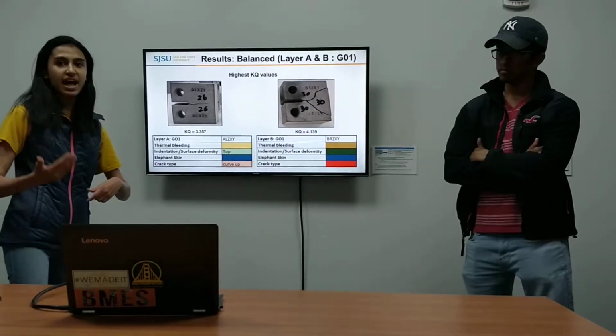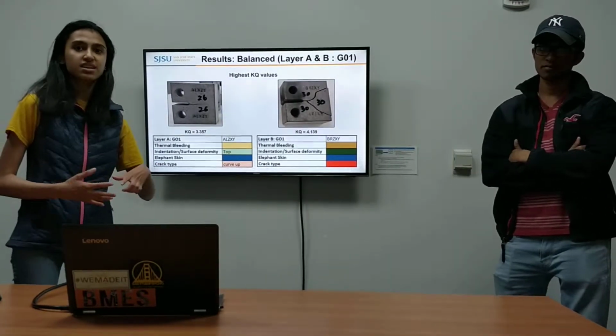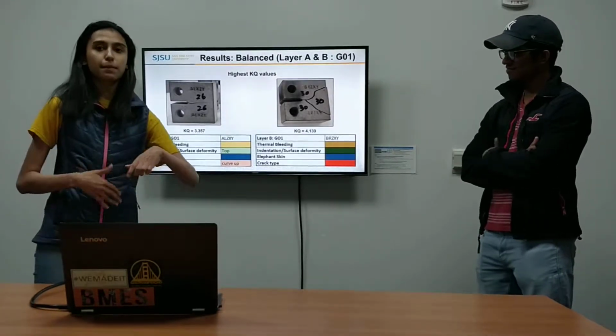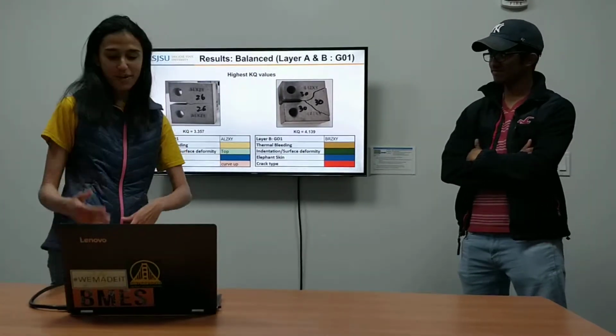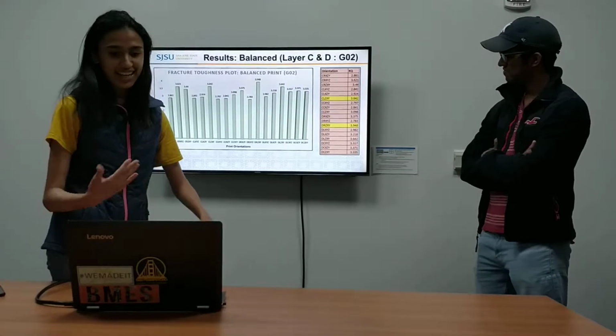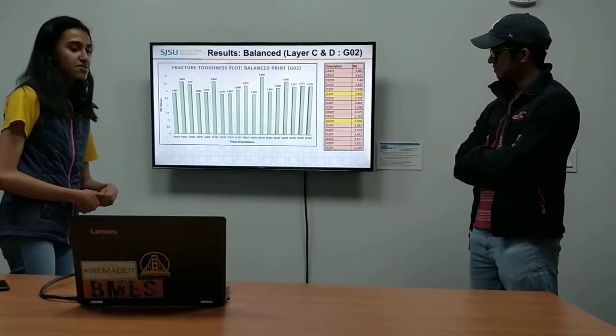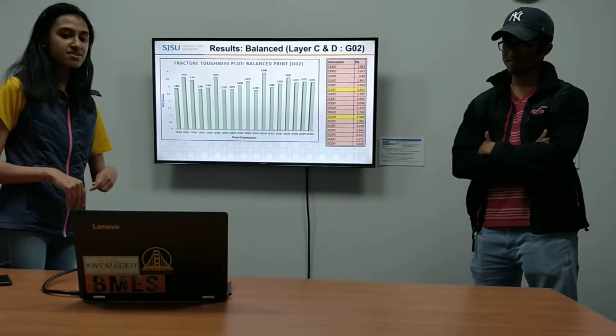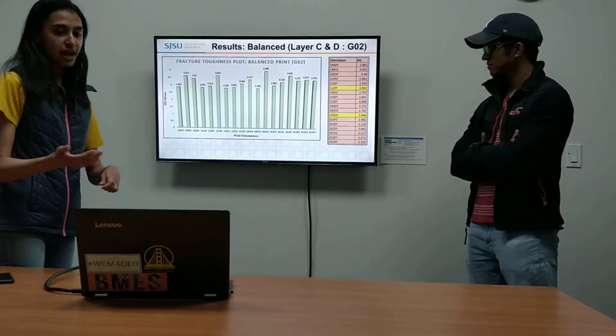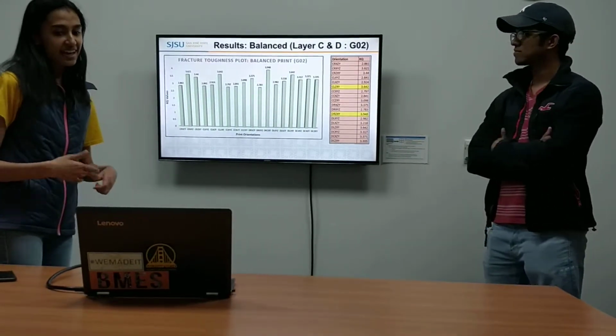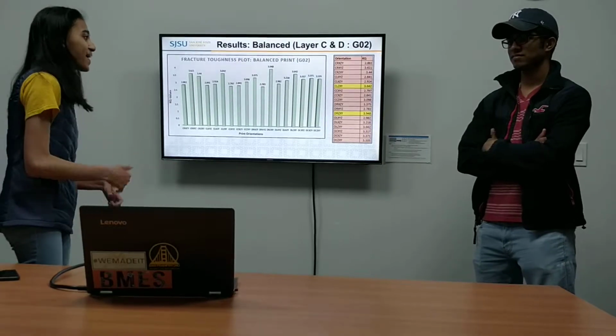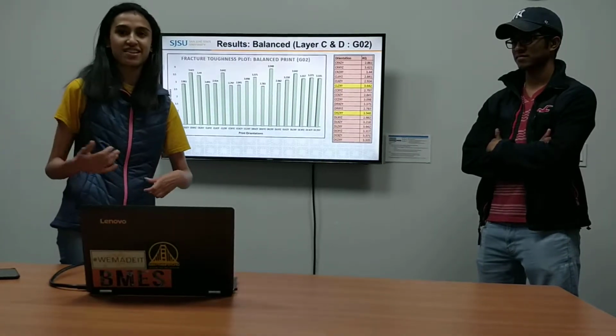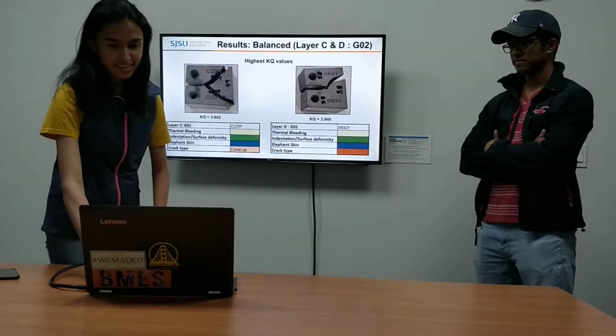So the top layers had less deformities and less indentation compared to the layer in the down part. And again, this is for C and D layers. Each print setting had 4 layers. So this graph represents the C and D layers. Again, we found that CLZXY and DRZXY produced the highest fracture toughness.